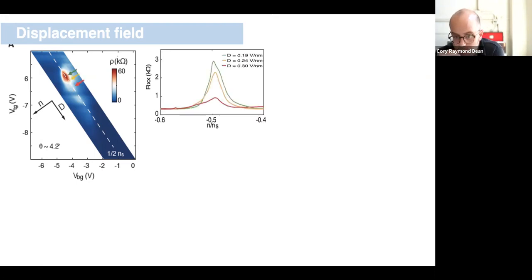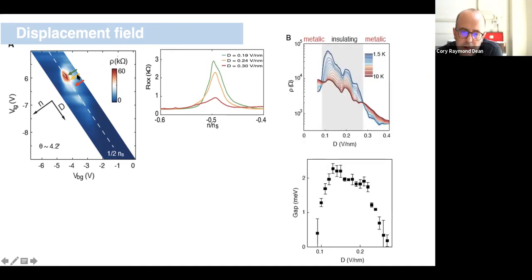Okay, so here I'm showing just some line cuts demonstrating that as a function of density, indeed, I see a resistive peak at different displacement field values. And here I'm showing that we can extract the energy gap associated with this peak. It really, again, shows an insulating-like behavior. So just through activation measurements, we can extract a gap value.